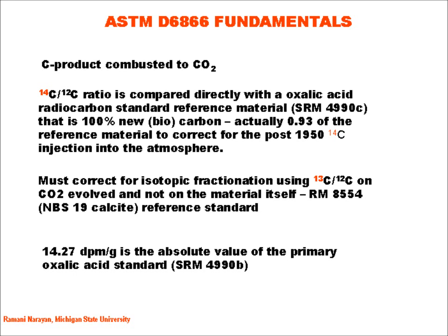Take a carbon product, you combust it to CO2, you measure the carbon-14 to carbon-12 ratio, you compare it directly to a standard oxalic acid new carbon product, a 100% biocarbon product, and therefore you can calculate the amount of biocarbon present in your product.